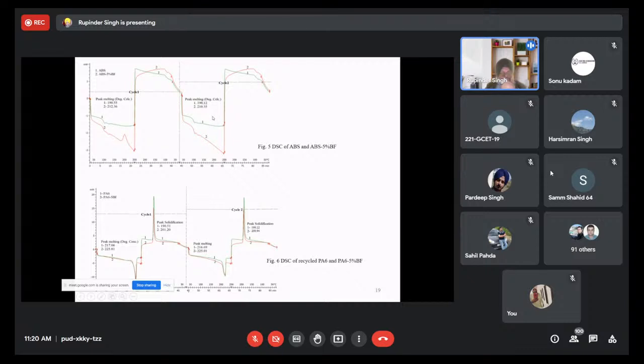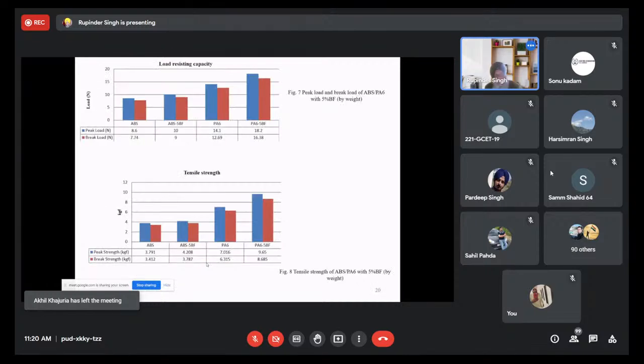That means in the repeated thermal cycle, the material is going to behave in a similar way. And I can consider this reinforcement as a thermally stable reinforcement. Similarly, we observed it for the polyamide. Without reinforcement, the melting was at 217. After that, it was at 225. And in the repeated cycle, again, it was similar. So I can consider this type of material as really a thermally stable material.